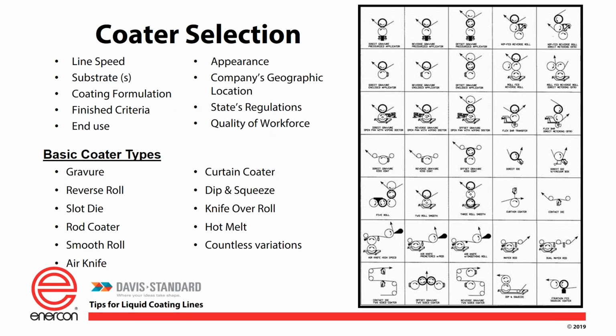Dip and squeeze, that's where we're going to dip the web into a tank of coating and then squeeze it between two rolls. On tape lines like masking tape, this is how you would treat the crepe paper, and you would saturate it with a coating that would give you the elasticity and a release factor for your adhesives. Knife over roll is another method that was usually older technology. This is where you put a precision knife edge right above the substrate, and the gap of that knife to the substrate creates your coat weight, but you fill a pond and then this just scrapes it off. It doesn't give you any good appearances, whereas the reverse roll, by changing speeds of the applicator roll and the metering roll independently, we can create a mirror effect.